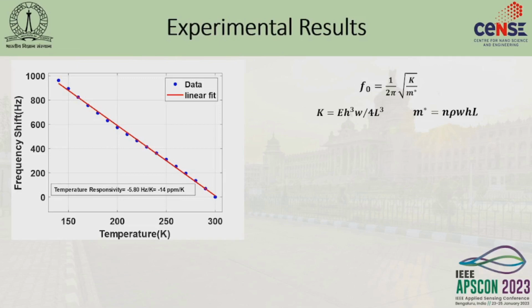And if we divide this value by the resonance frequency of the device, we get about minus 14 ppm per Kelvin response of this device. So, as I explained in the first slide, the resonance frequency of the device depends upon the stiffness and mass terms. The stiffness is proportional to Young's modulus and the geometrical parameter. Again, the mass depends upon the density and the geometrical parameter.